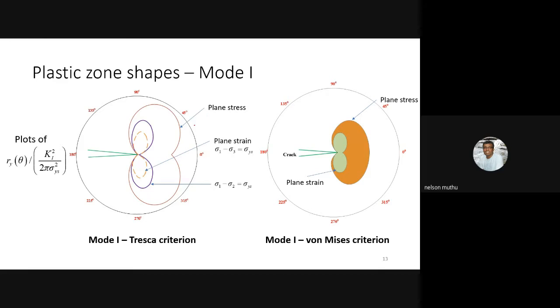For plane stress, obviously, as we have already seen, the size of the plastic zone is comparatively higher than what you have seen in plane strain. In plane strain, if you use the sigma 1 minus sigma 3 criterion, you can see the size of the plastic zone is so small. Whereas if you use sigma 1 minus sigma 2 is equal to sigma ys, it is slightly bigger. So essentially, the size of the plastic zone in plane strain is much smaller than in plane stress. This is for mode 1, Tresca criterion.